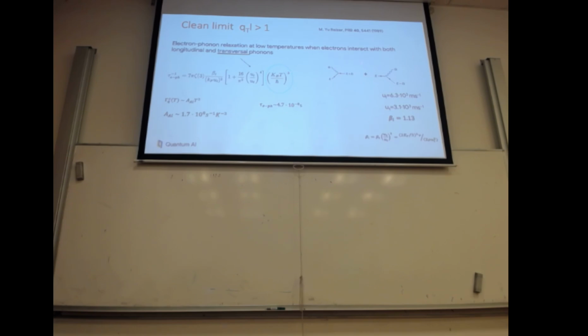First of all, he considered the situation in which he has a sort of high temperature, in which we have both absorption and emission of phonons. So we are not interested in this because we are at a very small temperature. But what he shows is that in the clean limit, the relaxation of the quasi-particle has a huge contribution from transversal phonons.